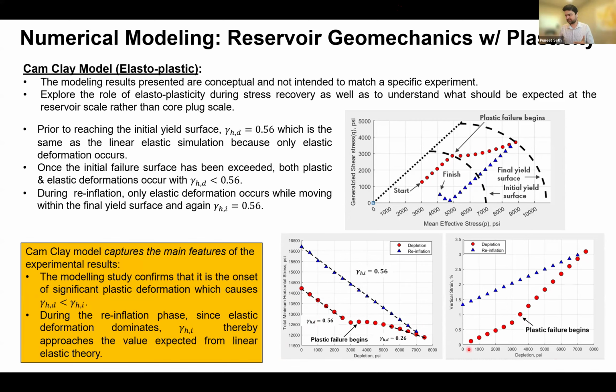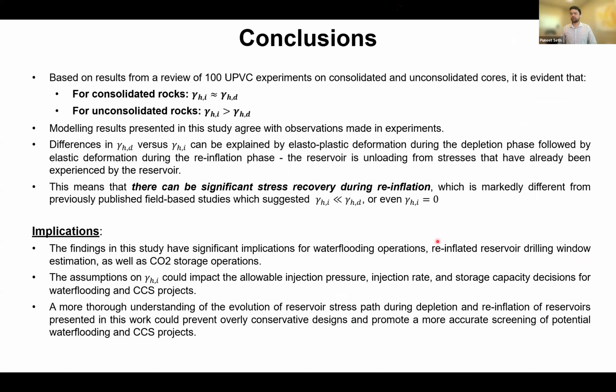On the strain side of things, it's also very clear what's going on. This is depletion in the elastic regime. Plastic deformation starts to dominate. You see a clear change in the strain versus depletion. During injection, again, we see that the slope of this line is basically the slope of this line because we are recovering elastic deformation. So to conclude, based on the results of 100 uniaxial strain compaction tests on both consolidated